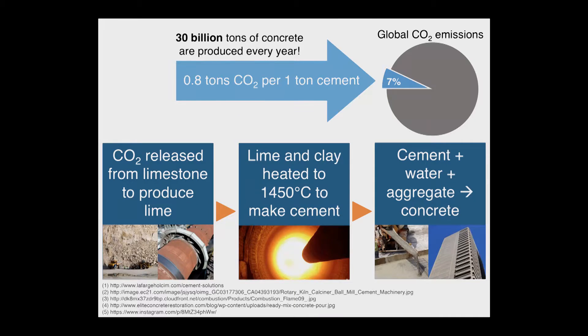Most of this CO2 comes from the releasing of CO2 from limestone to produce lime. The second highest source is the intense heat required to make cement from lime and clay.